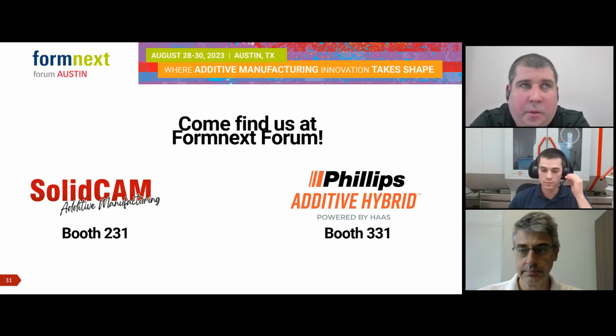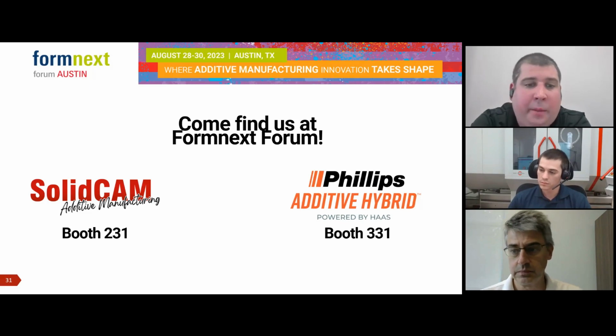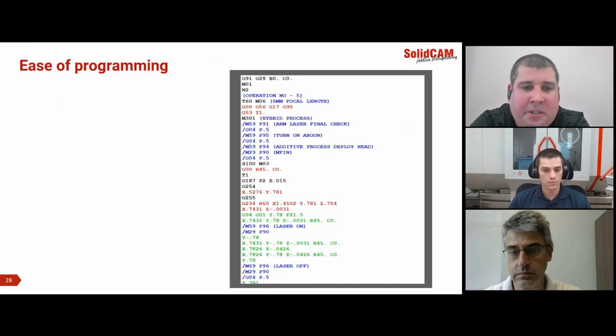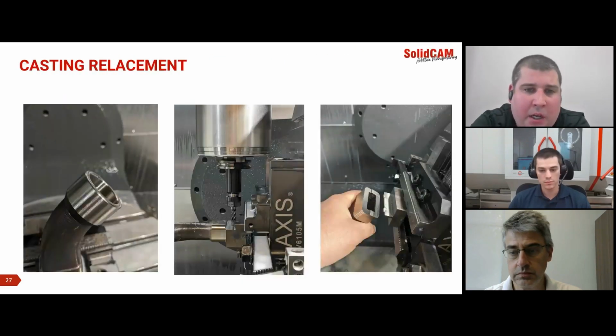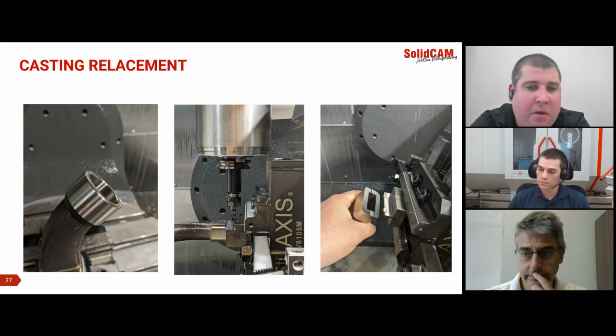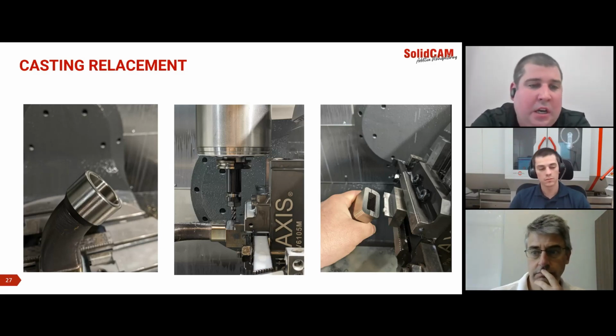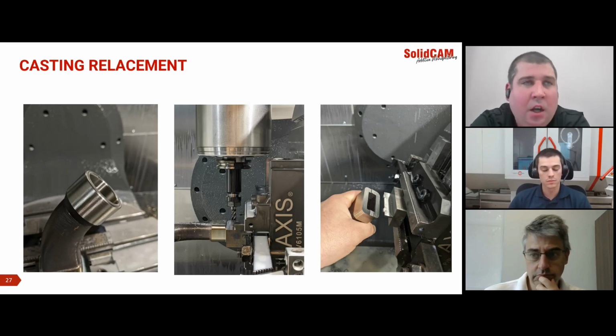Yeah, that's where you would certainly have to segment the toolpath. If we needed to machine the inside or outside of that curved geometry, especially for the inside, it's a physical limitation where you're not going to be able to get a lollipop style ball mill inside at a certain curvature. So that's where you'd have to print, maybe 15 degrees of that bend radius, and then machine the inside of it, start printing again.